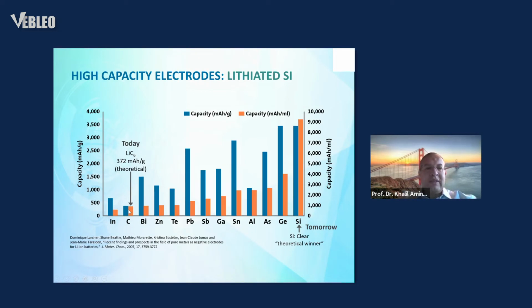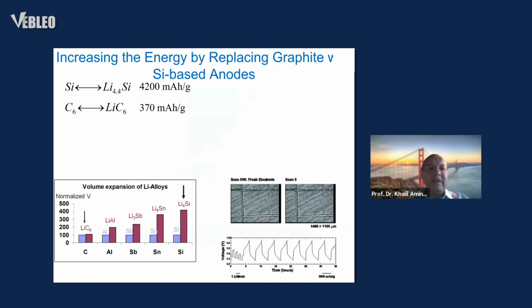Obviously, you cannot use 10 times because there is no way you can design an electrode that is very thick to absorb all that lithium from the cathode to the silicon. Now, the problem with silicon is that when you alloy almost 4.4 lithium, you have a significant expansion in volume. And this expansion can cause a major problem.